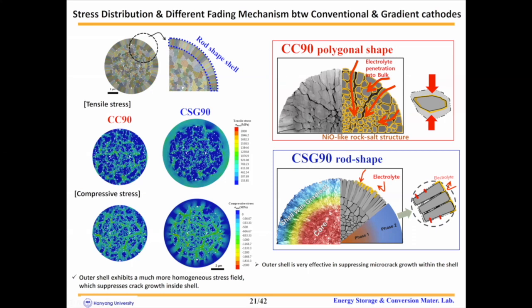As you can see, more importantly, the outer shell exhibits a much more homogeneous stress field compared to the CC cathode, which suppresses crack growth inside the shell. This is the capacity fading mechanism for the two cathodes. Based on this result, we conclude that the outer shell is very effective in suppressing micro crack growth within the shells.